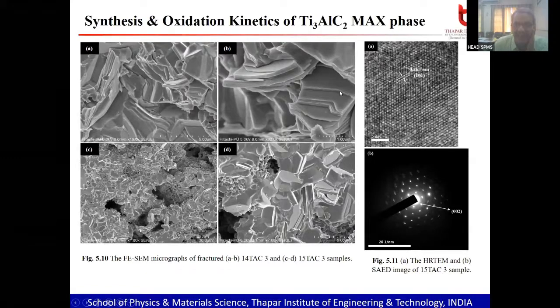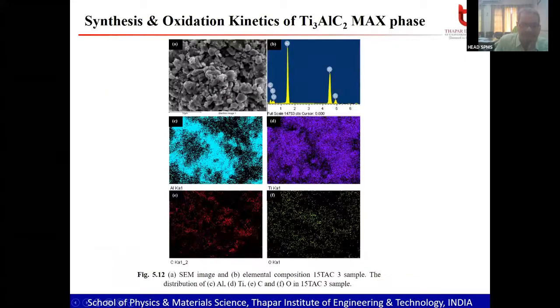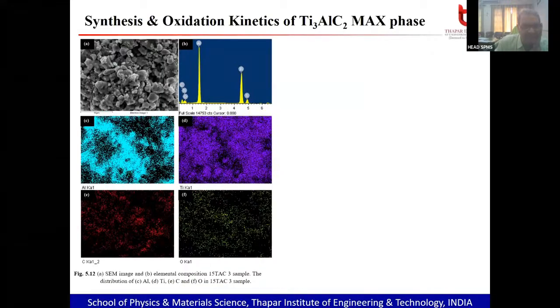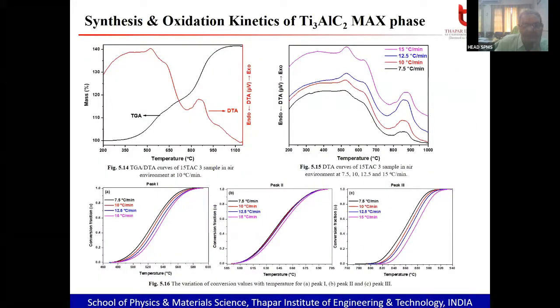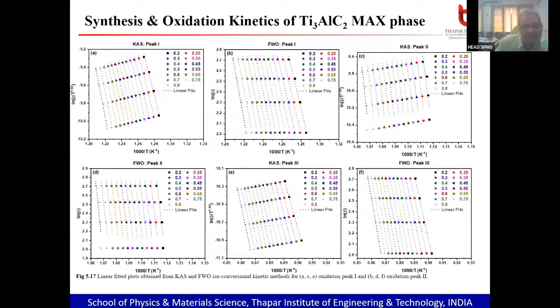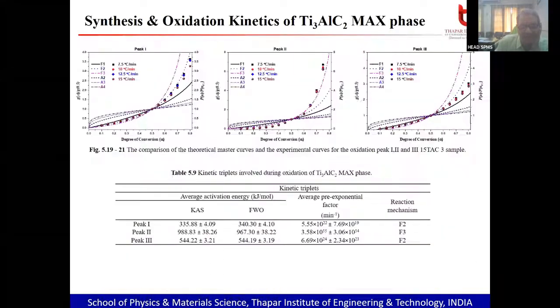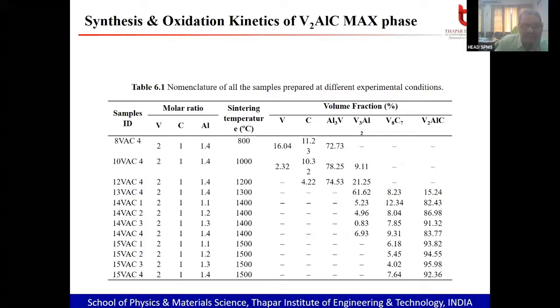You can see that this is the plate-like structure. Very layered structure. Here you will find that this is the layered structure. And this is the typical morphological feature of the MAX phases. You can see the bending phenomenon over here, bended. So this part we have successfully investigated. We have done the electron mapping also, uniform distribution of the elements, and also XPS analysis. Oxidation kinetics we have studied. After doing a lot of theoretical work, we could succeed in synthesizing this material.